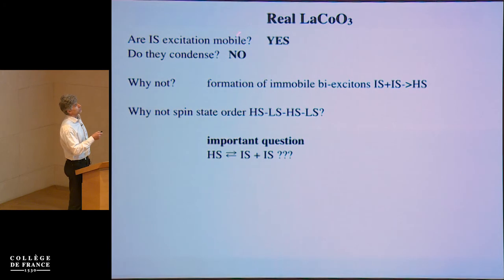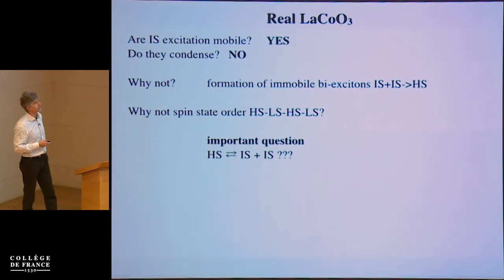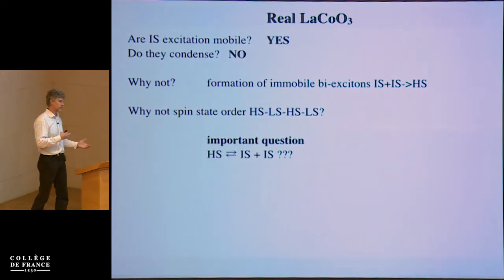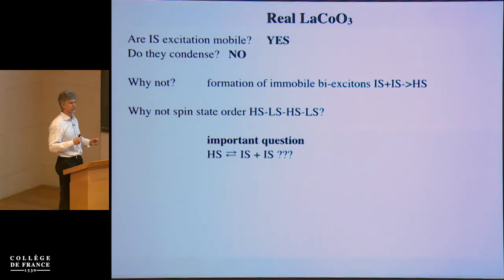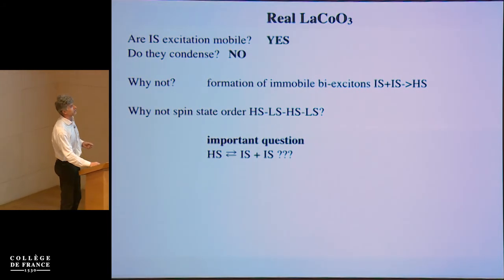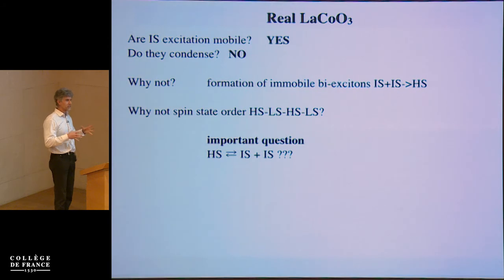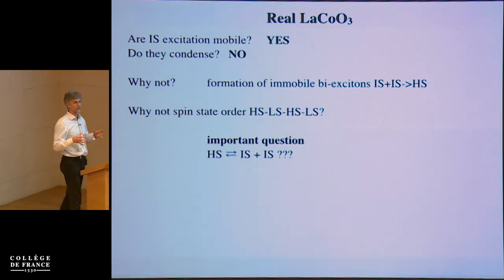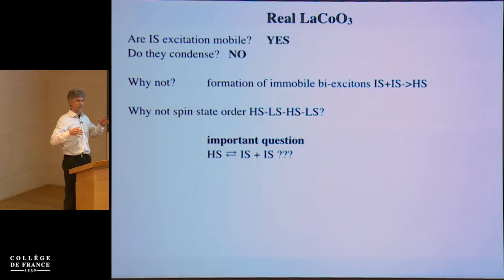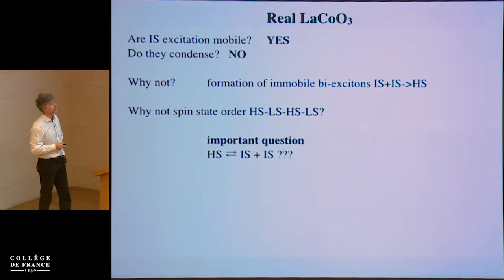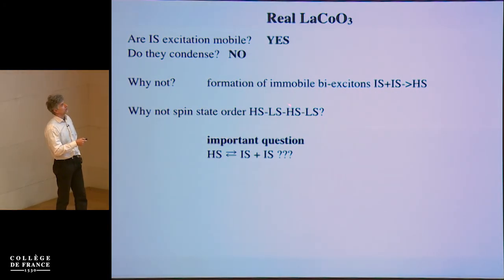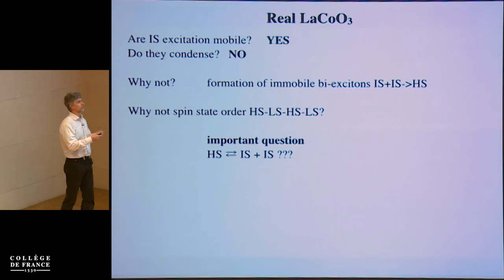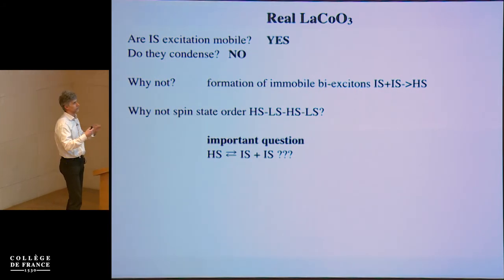Now, what is the problem for excitonic condensation in lanthanum cobaltate? Why is it probably hard to achieve in this material? The problem is that our excitons, which are the intermediate spin excitations, are actually strongly interacting with each other. They tend to form high spin states, which in our language are bi-excitons. So this is a situation where we have a strong intermediate, strong exciton attractive interaction.